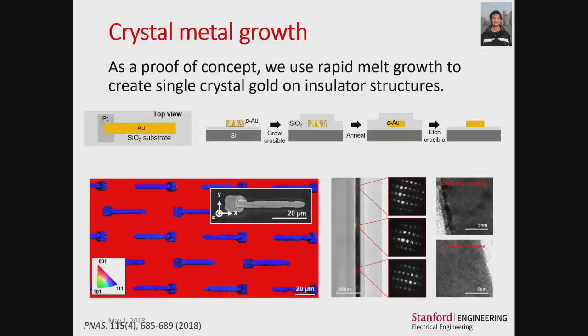And just to walk you through, we have a similar type of process here, where we start with a platinum seed with a gold stripe. We encapsulate it in silicon dioxide to form our microcrucible. We heat it to the melting point of gold. And as the gold cools, it undergoes liquid phase epitaxy, and ultimately we get single crystal metal, at which point we can etch away the crucible.